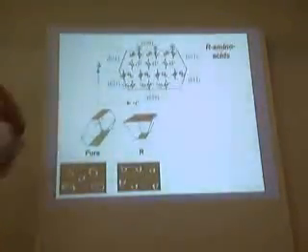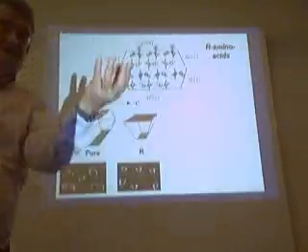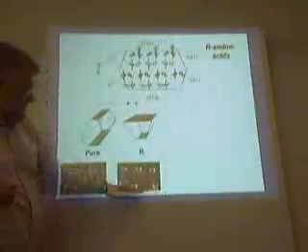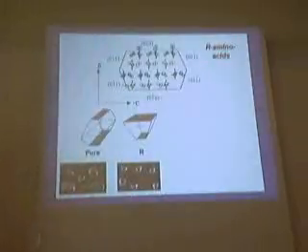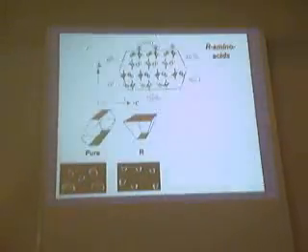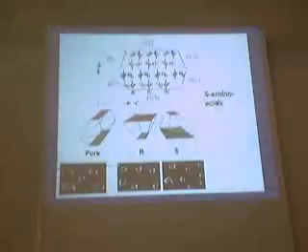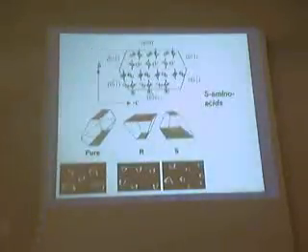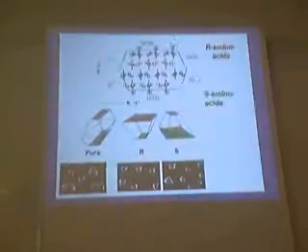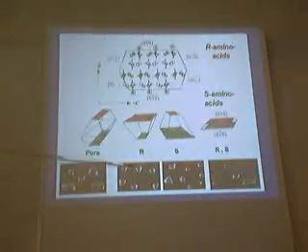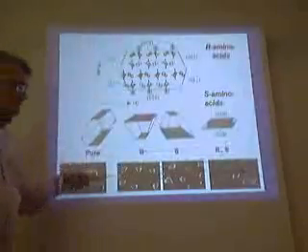If you impede the growth of a certain phase, you actually increase its surface area. If you take the S amino acid, you get an enantiomorphous chirality. And if you do this with the DL, you generate a plate of the RS.